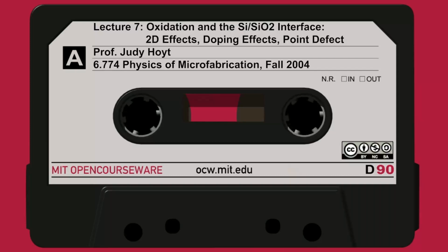QF, remember, fixed charge doesn't change with bias. The density of interface states that changes is believed to be associated with dangling silicon bonds right at the interface. And we can passivate these, because they're not in the oxide, they're right at the silicon dioxide surface. We can passivate these by adding hydrogen. So when you build a CMOS or a MOSFET, the last step is 450 degrees in hydrogen ambient. The hydrogen diffuses in, it satisfies these dangling bonds, it bonds here, and it covers up that charge.